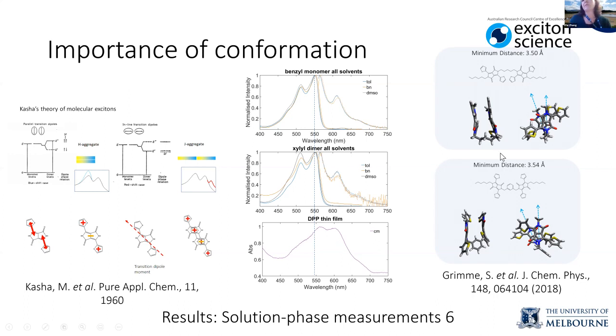I also just wanted to say that we had a colleague here at the University of Melbourne, Dr. Lars Gehrig, and he did some ground state calculations for us. And so this is DFT calculations that incorporate London dispersion forces. So in a molecule that has a dipole like this and where these pi-pi interactions are pretty important, you have to take into account these forces. And he showed that all of the dimers are folded in the ground state, but that there are a lot of different conformations that are thermally accessible. So it's very possible that there are a range of different conformations and that this kind of broad heterogeneous model that we proposed before could be right.